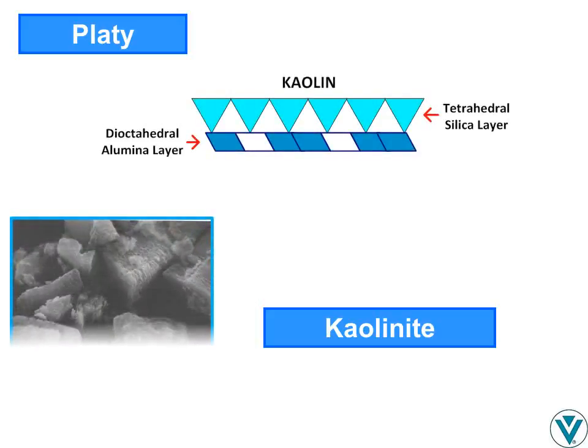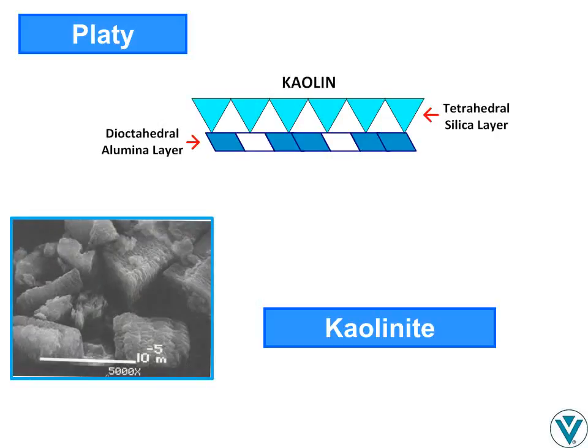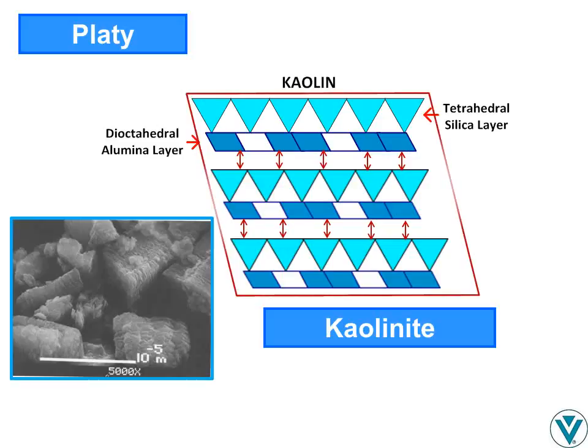The prototypical 1:1 di-octahedral silicate is kaolinite. The continuous sheet structure produces thin particles which exist in nature as overlapping flakes. These can occur as books which under magnification resemble stacks of paper. Kaolin crystals are bound via hydrogen bonding of the octahedral layer hydroxyl face of one plate to the tetrahedral layer oxygen face of the adjacent plate. Separation into individual clay plates is therefore difficult, but is accomplished by mechanical means to produce delaminated kaolin. A tetrahedral sheet and octahedral sheet are actually very slightly mismatched, and this mismatch induces curvature in the structure. The kaolinite tetrahedral sheet is rotated slightly for better oxygen sharing, and the tendency to curve is inhibited by hydrogen bonding between kaolinite sheets.